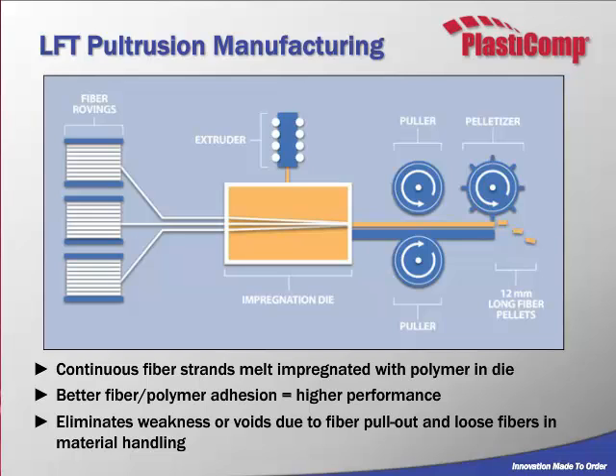We can typically manufacture material that will go from 20% in fiber content by weight all the way up to 60% by weight. In some cases 70%. It's by weight. It's dependent on the fiber type and the polymer we're working with. And that is controlled by the size of the exit orifice. Once the material exits, it's cooled and then chopped, and the resulting pellet length is typically 12 millimeters. However, that can be chopped to different lengths if necessary.